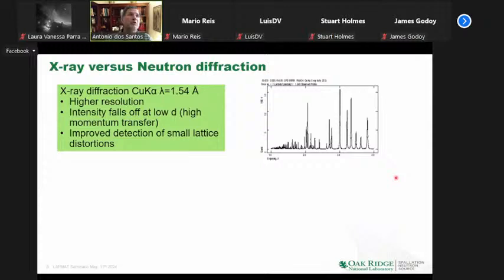I wanted to add this slide to this talk because I wanted you to see the contrast. This is what you'd measure in a laboratory. This is some random compound, I think a lead sulfide, and you can see it's pretty sharp. You can see the peaks, but it decays, and this is the d-spacing. So this can give you a sense of the spatial resolution. You barely have any signal left as you go out in Q at higher momentum transfer. You can see shoulders, and so you can really ascribe the space groups and small lattice parameter distortions. Even a lab source is good for that.